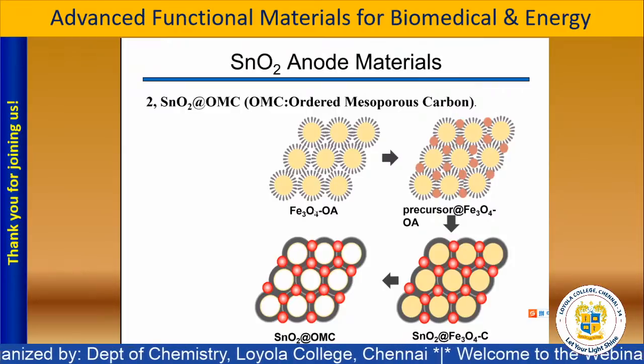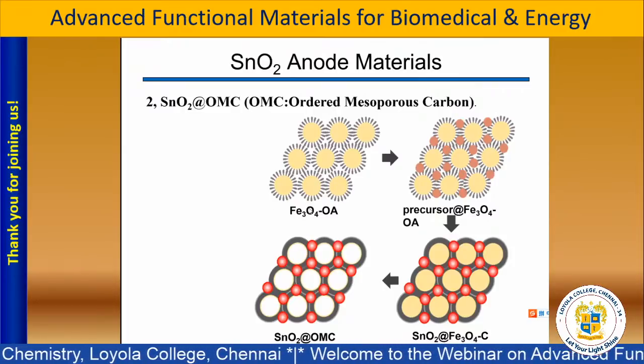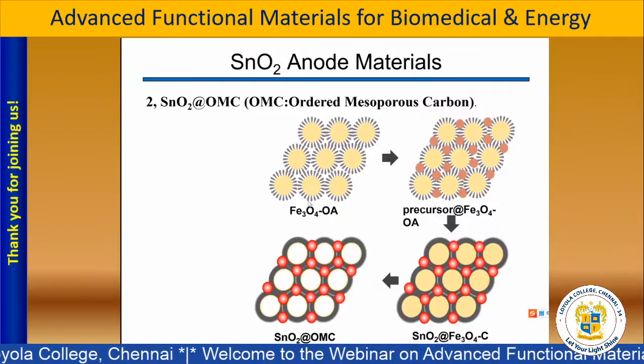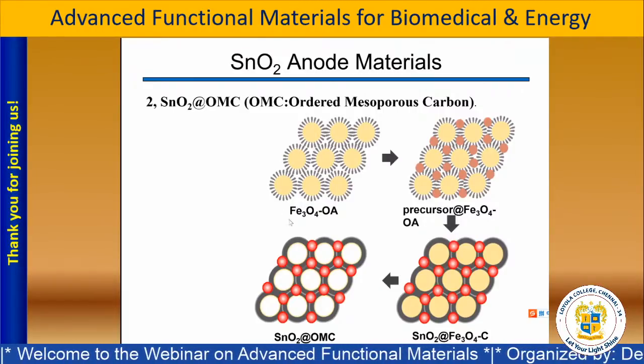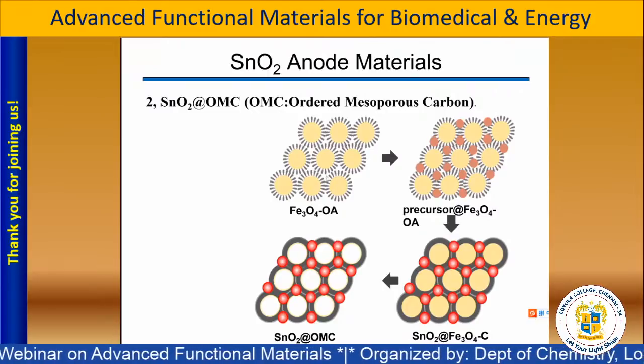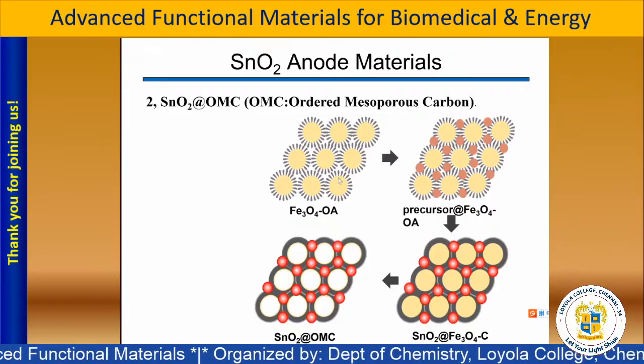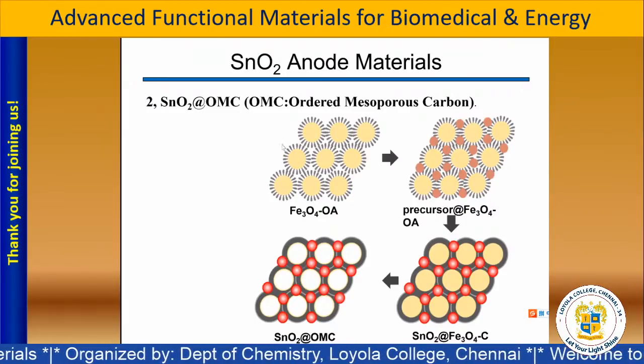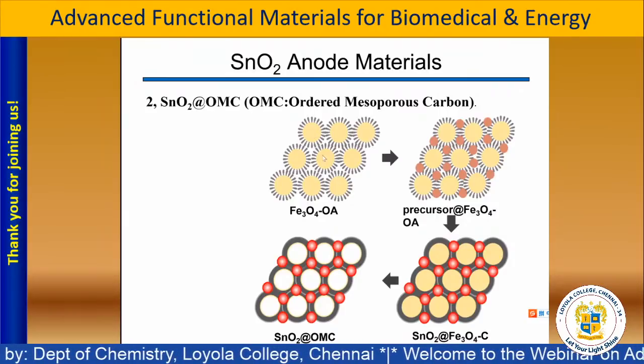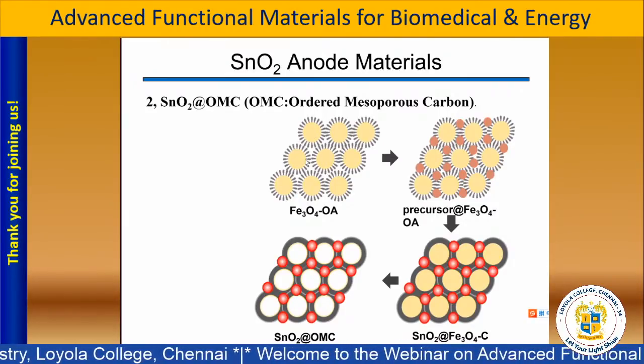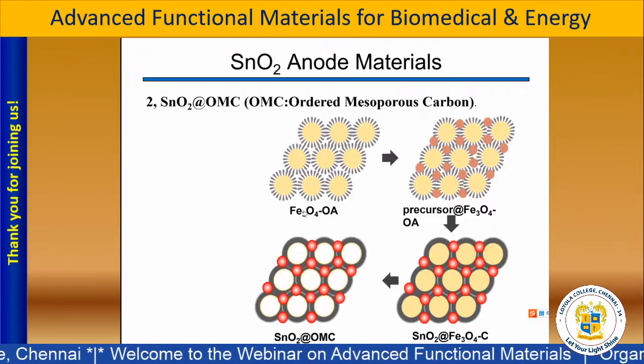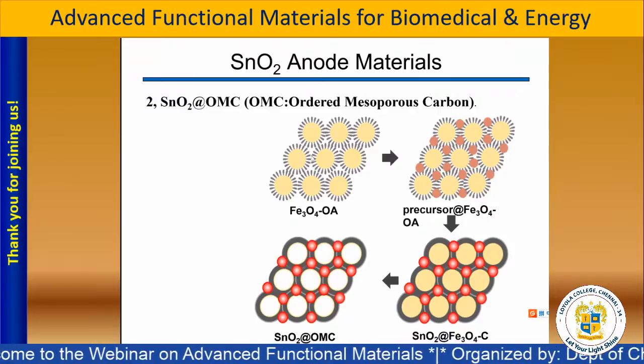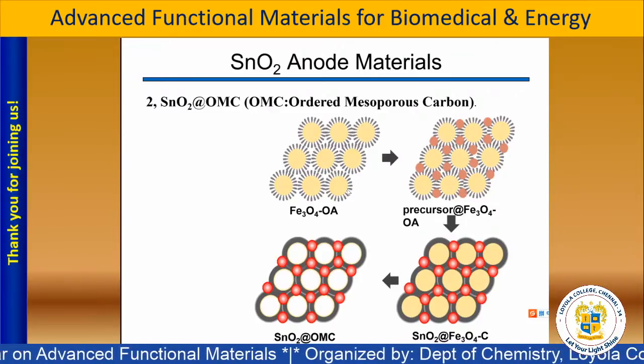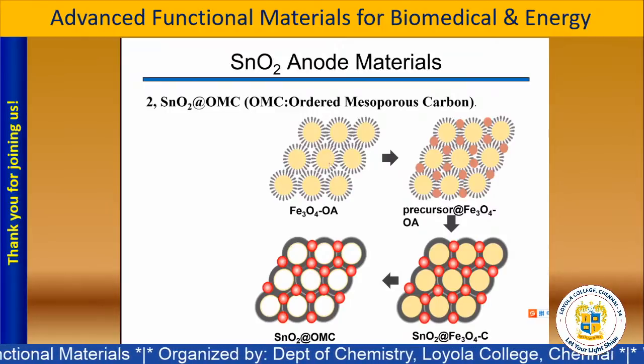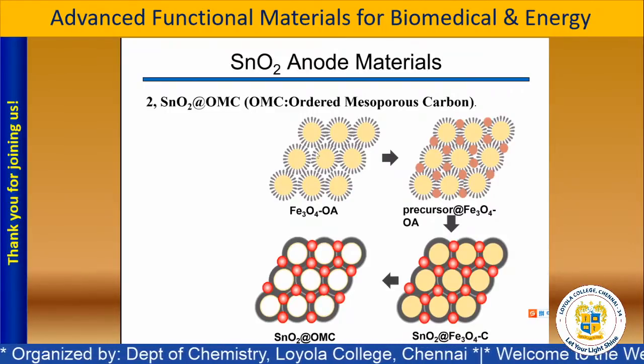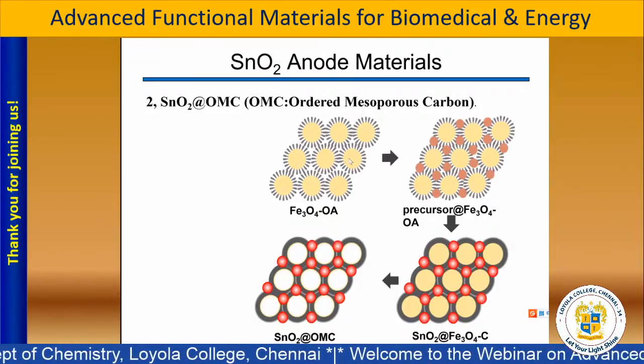We can get the ferroferric oxide with about 15 or 20 nanometers. It's very easy to get it, and then we use solvent evaporation to get this structure. This structure is the orderly arrangement of the ferroferric oxide. Because during this evaporation, the ferroferric oxide will self-assemble into an arrangement. So, in the end, the material will copy this structure.